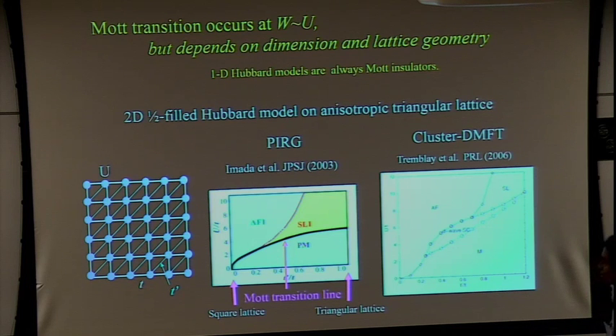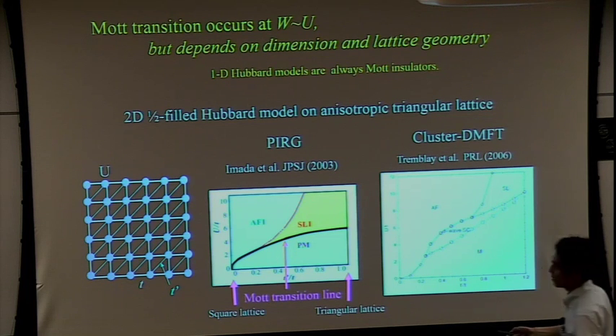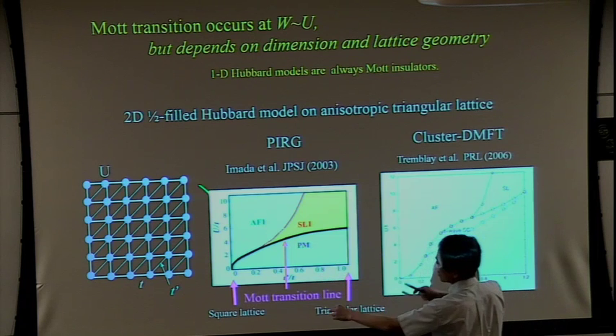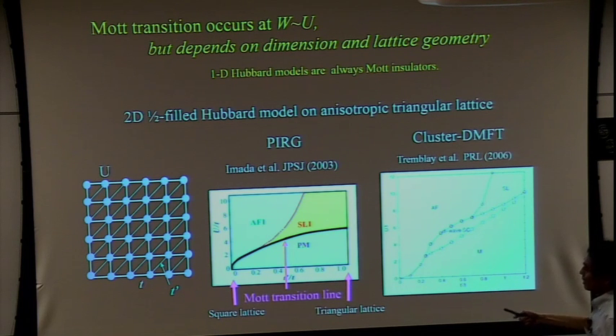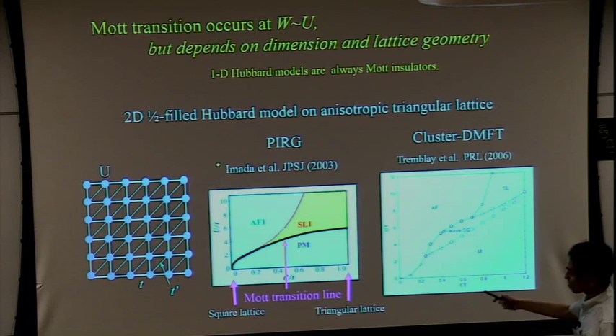Roughly, these two phase diagrams give a similar profile. Namely, this is T prime over T and U over T. This calculation assumes a lattice geometry of a square lattice with transfer integral T, and this diagonal transfer integral T prime is also present. They change the ratio of T prime over T as a parameter, and U over T is the strength of correlation, the correlation strength, as the vertical axis.